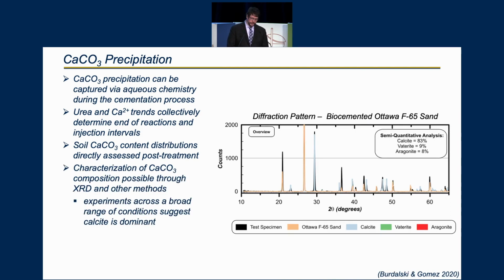And further characterization of this produced calcium carbonate can be possible using things such as XRD and other methods, which suggest that under most reaction conditions, higher stability calcite is the predominant mineral phase generated during MICP.